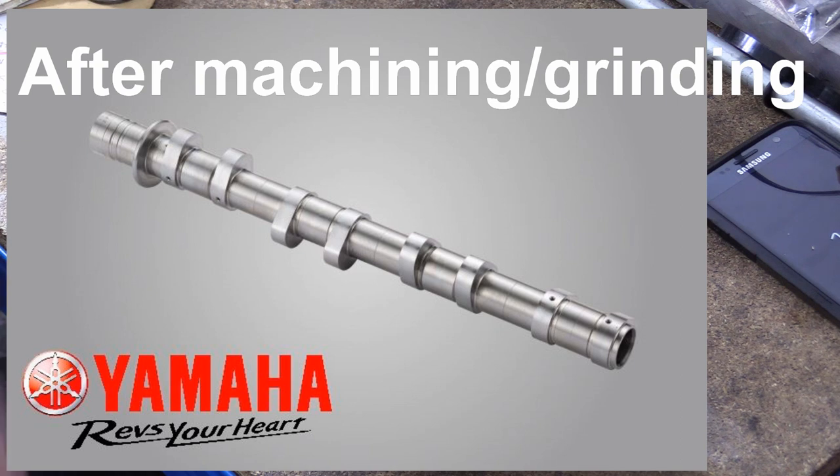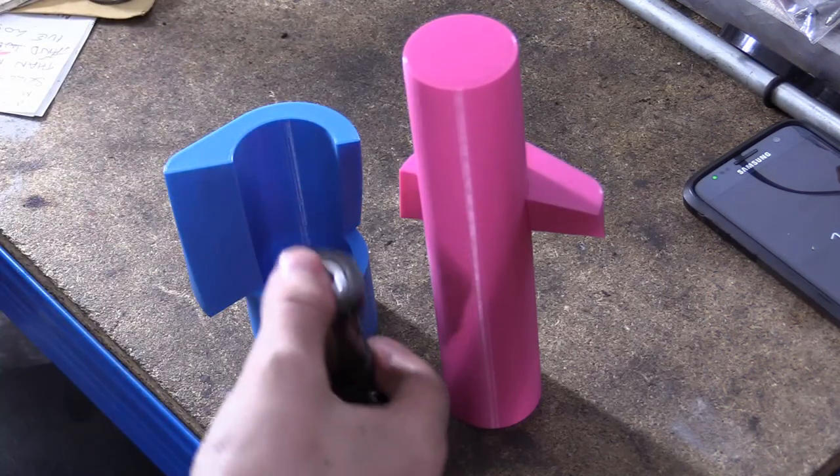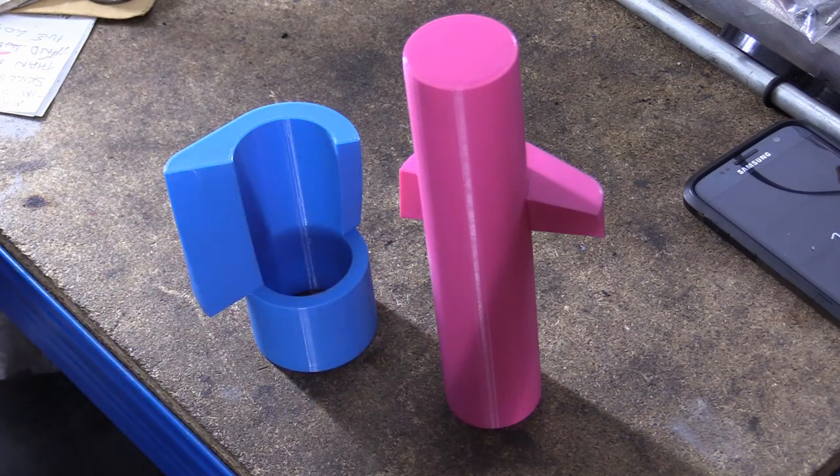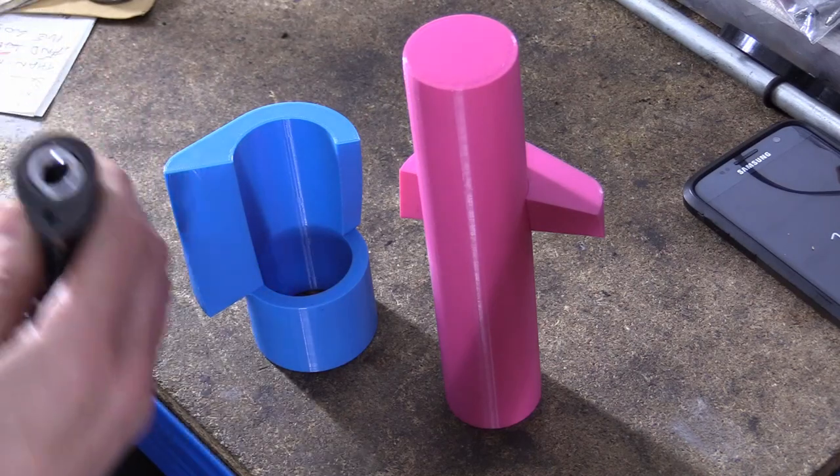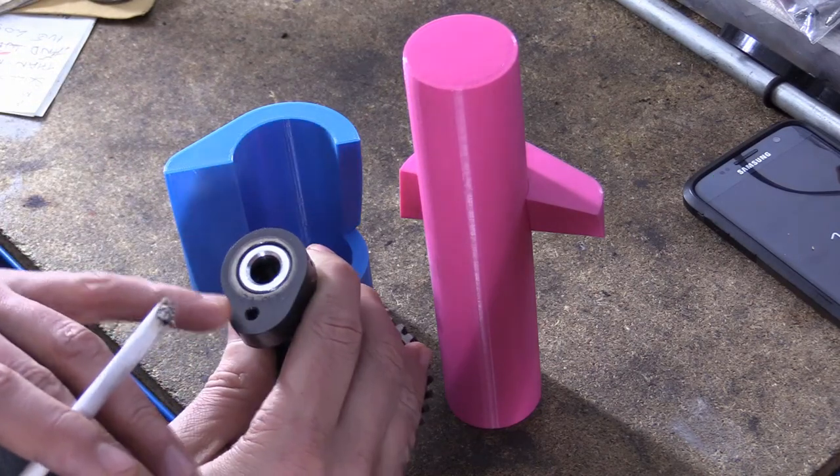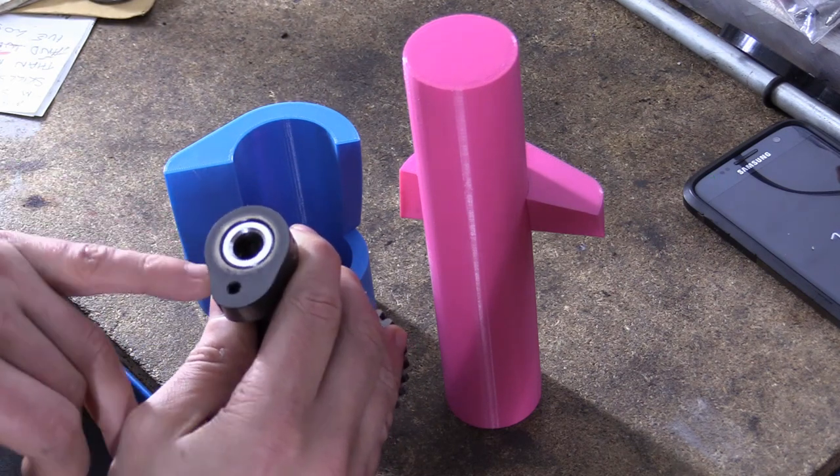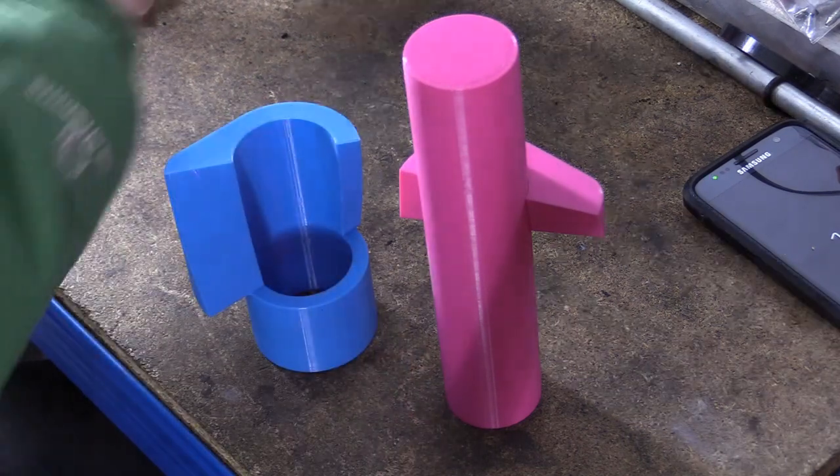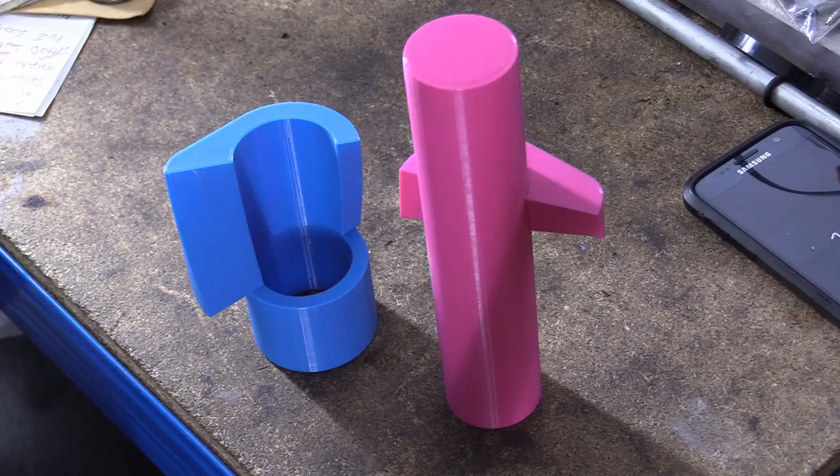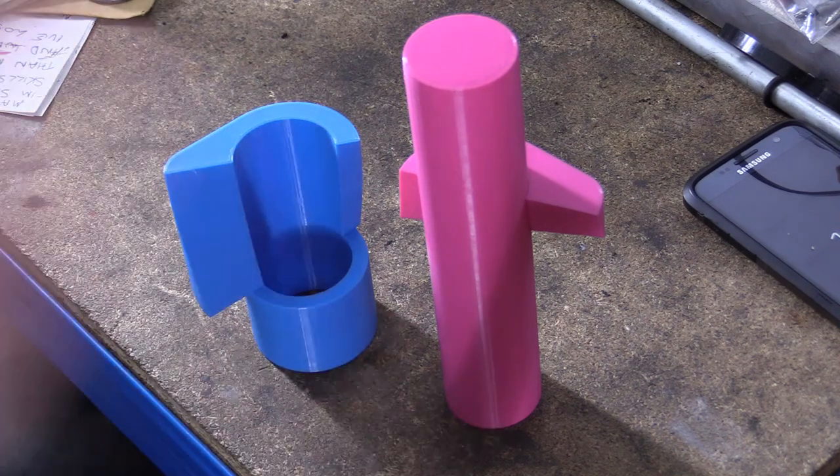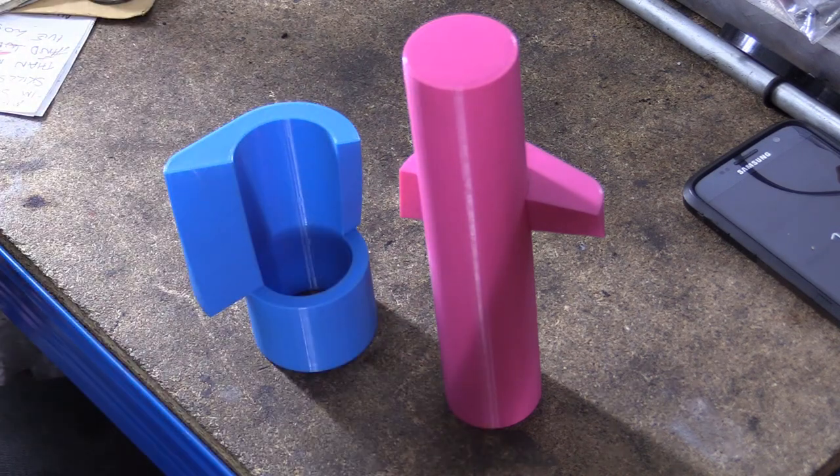Wearing, absolutely fantastic. Here's a BMW camshaft and these surfaces will be hardened like you wouldn't believe. You can actually see it. You can see where the steel color from the inside, you can see that the color's different to this outside. This has been induction hardened, same as this bearing surface. This is to stop it basically wearing out prematurely.